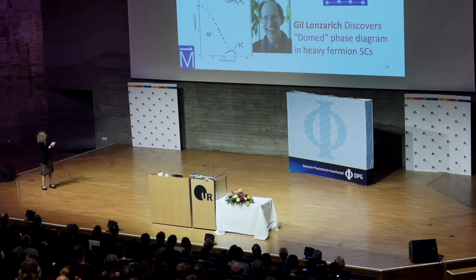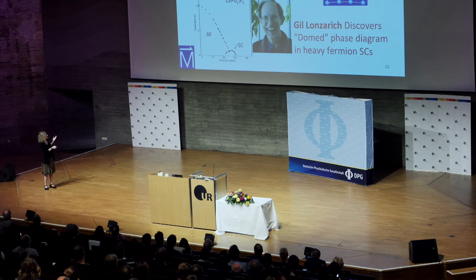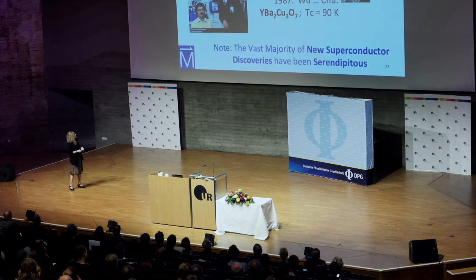Gil Lonzarich took one of these heavy fermion materials and just put a lot of pressure on it. And that was the first time that the superconducting dome was seen. So what do we see now? Magnetism is good, an antiferromagnetic Fermi liquid. For some reason, you want to be near a magnetic quantum critical point, and all of a sudden, it's very clear that the electron-phonon BCS theory is not holding.